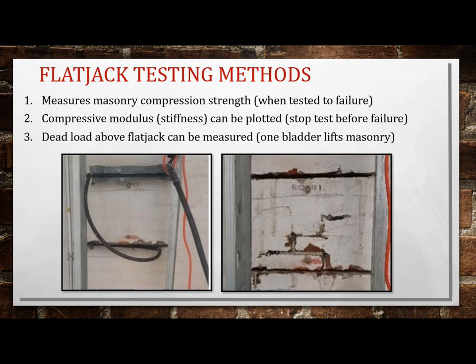So there's three techniques that we use with this. One of them is to measure the compression strength, kind of like what we did on this test here where we took it to failure. The second one is to determine the compressive modulus, the stiffness of the wall. You don't take it to failure, but you stop before that, and you do repeated tests at different force levels. And sometimes our system maxes out before it cracks. And so in that case, we go to technique 2, you do repeated tests, and so you can get enough data to draw the curves you need.